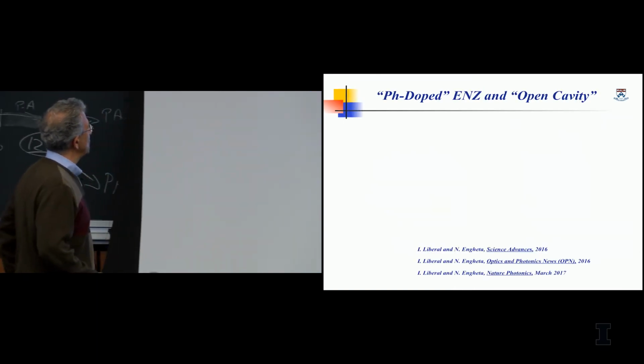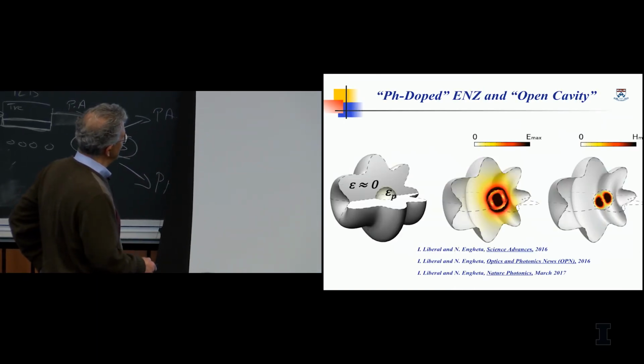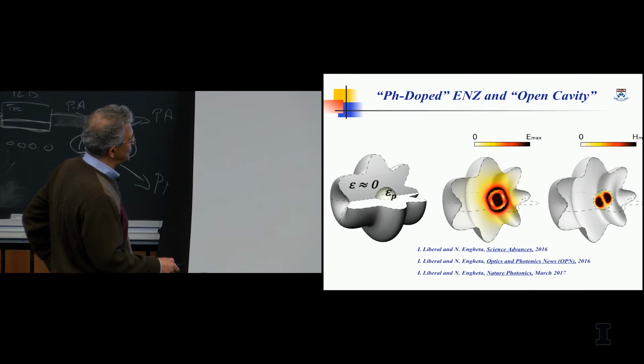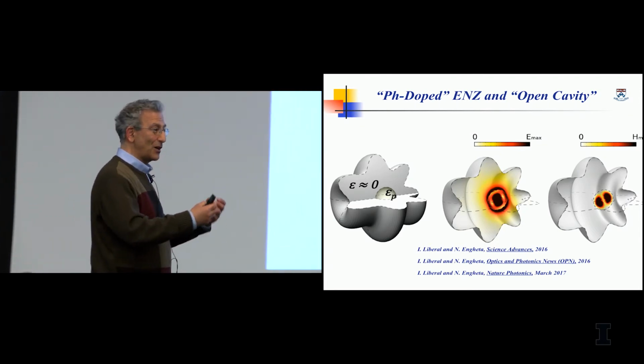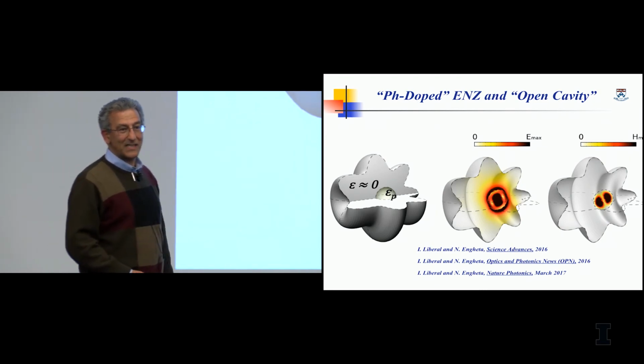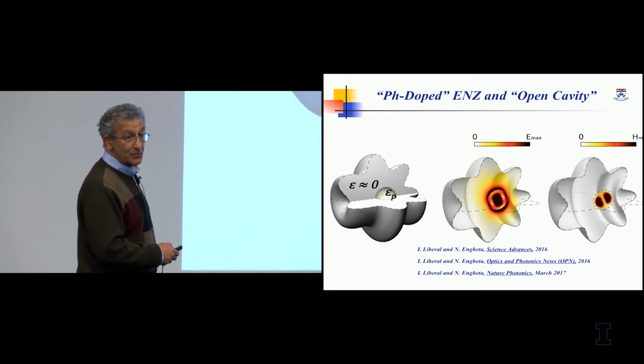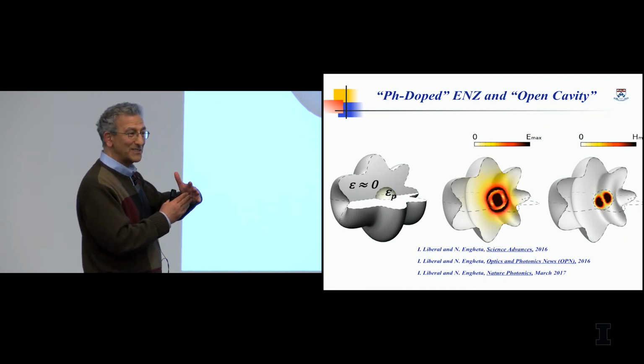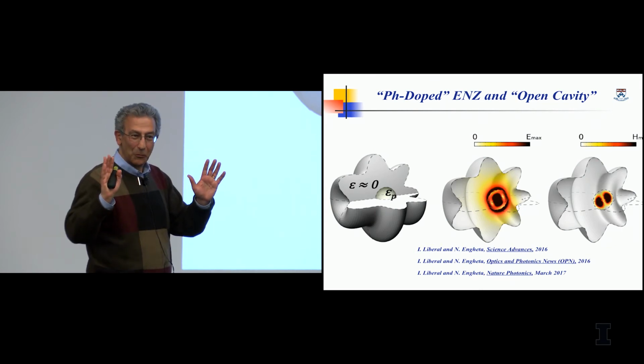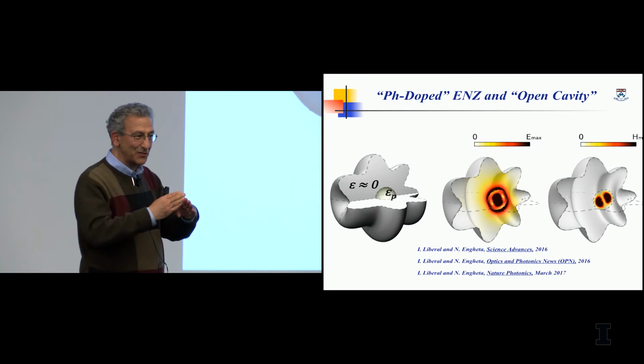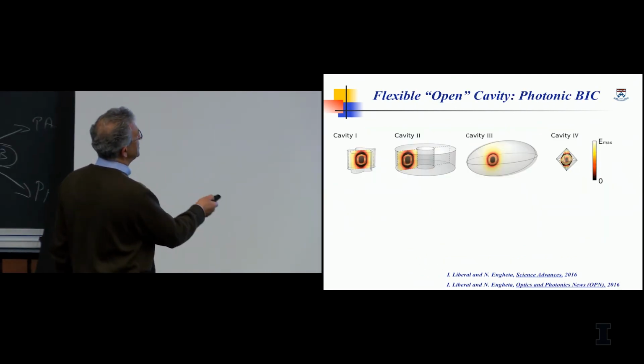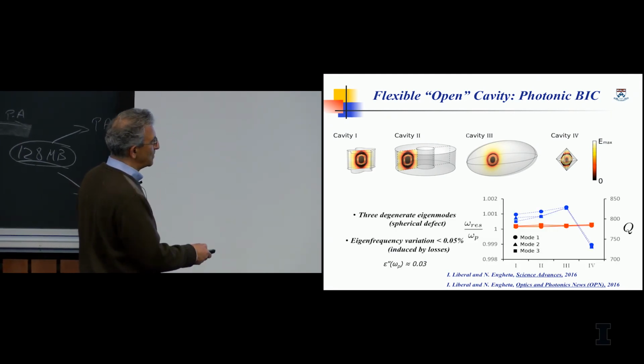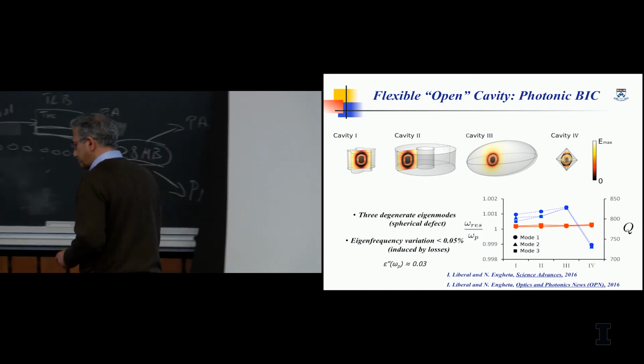Anyway, the cavity I promised to show you is that you can have cavity structures like this with arbitrary cross-section, arbitrary shape, such that you can have a very interesting mode inside. This is an electromagnetic mode where inside the dielectric you have magnetic and electric field, but in the ENZ region you only have electric field, but no magnetic field. This is the decoupling I mentioned to you, that you can decouple E and H. This structure can actually hold electromagnetic energy even though the boundary is open. The reason is that the electric field comes over here and has only a normal component. But when you sit outside the structure, the electric and magnetic field is 0. And the reason you can do that is because epsilon is 0, so vector D is continuous. You can have very different cavity shapes, but all of them with the same resonant frequency.